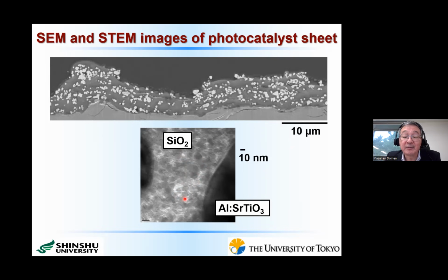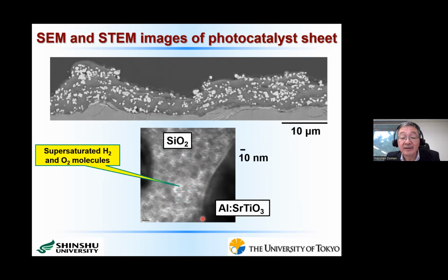But there exist these kinds of buoys, and these buoys are actually filled with distilled water. In addition, evolved hydrogen and oxygen molecules are dissolving in this distilled water, but that is actually a supersaturated condition. The reason that this hydrogen and oxygen does not form bubbles is that this void is too small to make a seed of the bubbles. So these supersaturated molecules go outside to the upper layer like this one, so this layer close to the surface is a supersaturated layer. Then the bubble is actually formed on the surface of our photocatalyst sheet.